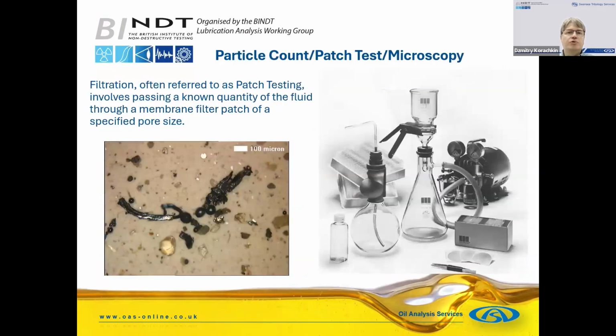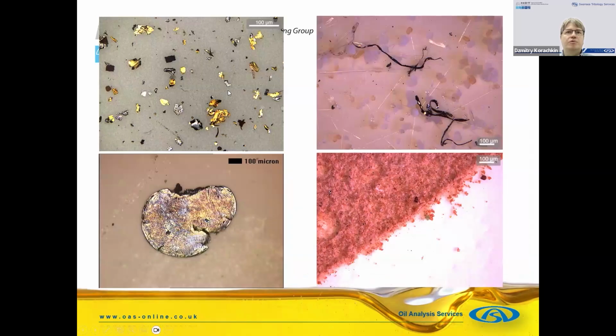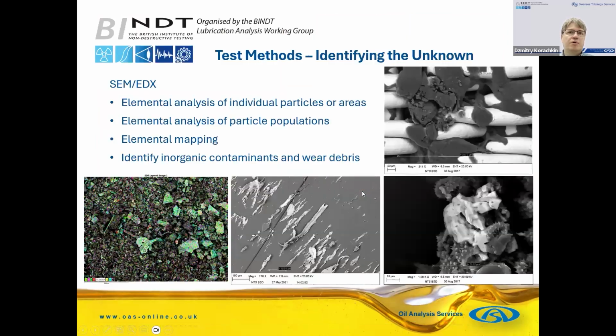particulates, but it's also useful to separate the more solid contaminants, or sometimes sludges, fibers, and so on, onto a filter membrane for further examination, either microscopic, and you're able to see quite a lot of difference between the different contaminants you have. Some copper-based wear particles, and you have cotton wear particles, you have some fibers from filter media degrading. You can get a lot of information from just looking at the contamination.